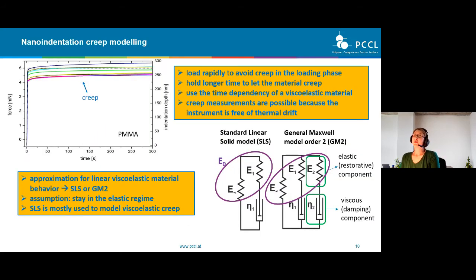So what we also did on PMMA were creep measurements. Creep measurements are done by loading rapidly to avoid creep in the loading phase, and then holding for a longer time and letting the material creep in this longer holding phase. And this you can see here on the left side, that the material here is creeping, so the indentation depth is going up. And this creep, or this time dependency, we can use for viscoelastic material modeling, which you can see here on the right side.